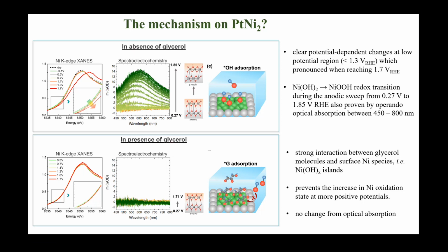And we've seen, very interestingly, that when we work in the absence of glycerol, we really oxidize the nickel all the way to nickel oxyhydroxide while the OH adsorption is happening. This is nicely confirmed by XAS and also spectroelectrochemistry that we did in the group of James Durrant. And you really see how these nickel hydroxide islands that you would form anyway on the surface of this platinum nickel go all the way to nickel oxyhydroxide during the anodic step. But when you work in the presence of glycerol, you have such a strong interaction between the molecules on the surface and nickel that this actually prevents further oxidation of nickel at more positive potential, and there is no optical absorption change. It's a very nice correlation between XAS and spectroelectrochemistry here.